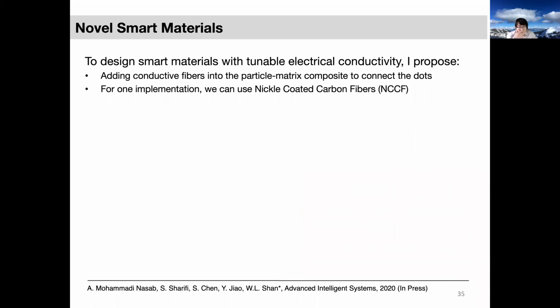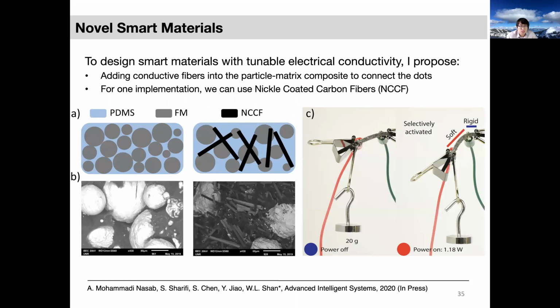Okay, so to design smart materials with tunable electrical conductivity, I then propose adding conductive fibers into the particle matrix composite to connect the dots. For one implementation, we used nickel-coated carbon fibers. This is a schematic of a 2-component composite, which is non-conductive as evidenced by many previous studies. We're adding this nickel-coated carbon fiber, which is highly conductive, because carbon fiber itself is conductive and is then coated by nickel. So these NCCF fibers will serve as bridges between these LMPA particles. And together, they're gonna generate this 3-component conductive composite, and you can do selective activation here.